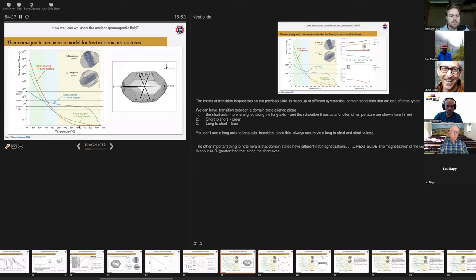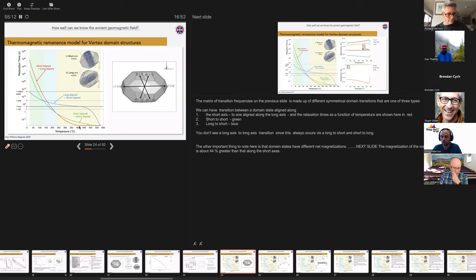If we imagine each of these temperatures sits for one minute, then we might get the domain states that are indicated where this relaxation time creates energy barrier with the domain states. So as you cool down, the first energy barrier for fast cooling, I'm calling one minute at each temperature fast cooling. The first domain state energy barrier is defined by the transition from the long to the short. So any grains that end up being aligned along the long axis can't easily move to the short axis. And at the time that the short axis remanence is available as a stable, if you like. So that's below about 200 degrees. So here we find a short or long energy barrier. So these are now stable. The short axis is now stable, but the problem is that everything's already locked in the long axis.